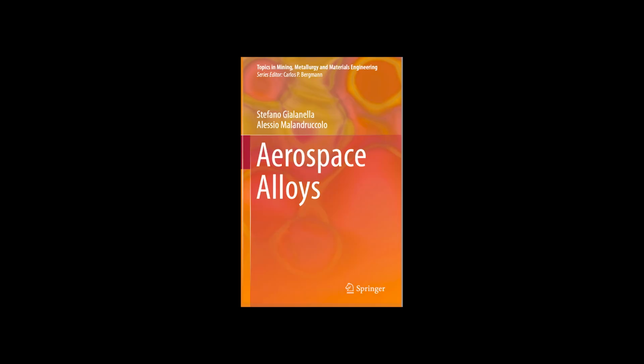And getting the initial metal really clean and uniform, the source mentioned VAR, vacuum arc remelting. Yes, VAR is super important for high-quality titanium. You basically take the raw titanium sponge, mix it with alloying elements, and maybe scrap, press it into a big electrode. Okay. And then you melt that electrode using an electric arc inside a vacuum chamber. The molten metal drips down and resolidifies in a water-cooled copper crucible. Why the vacuum? It pulls out dissolved gases like hydrogen and nitrogen, which can make titanium brittle. VAR also gives very controlled solidification, which minimizes segregation, meaning the alloying elements stay evenly distributed, and leads to a much more uniform, high-integrity ingot.